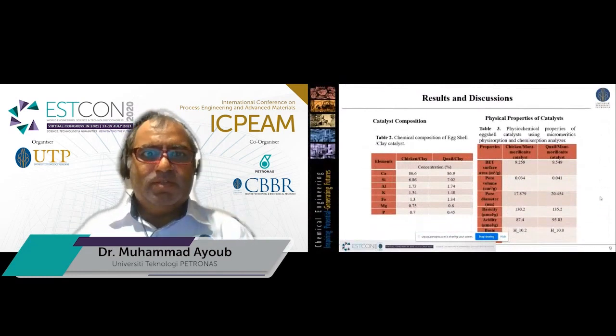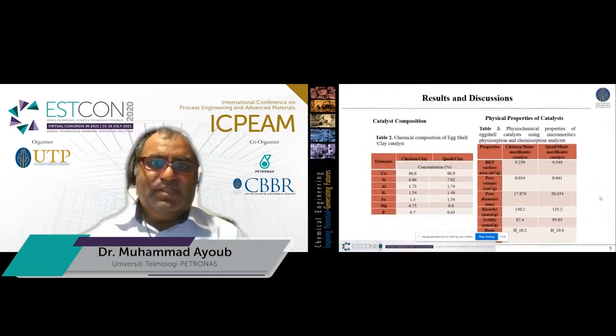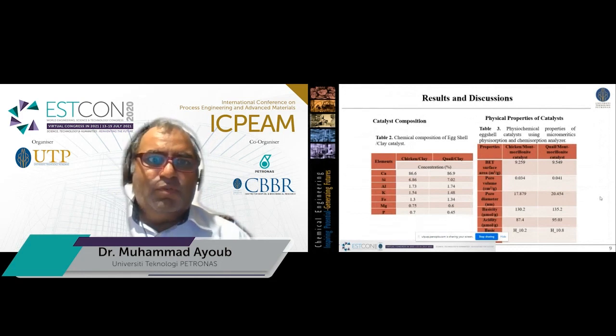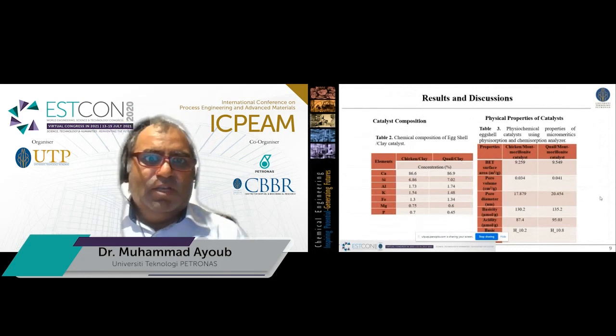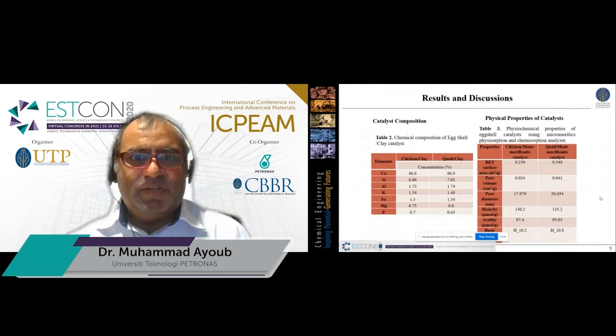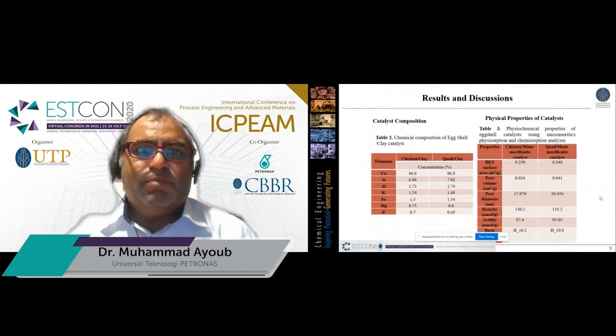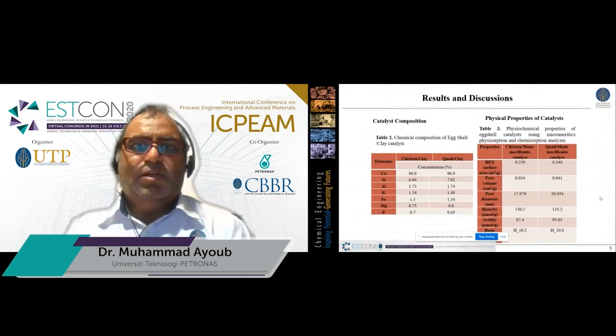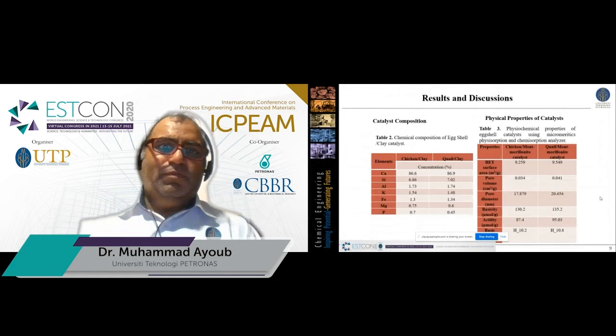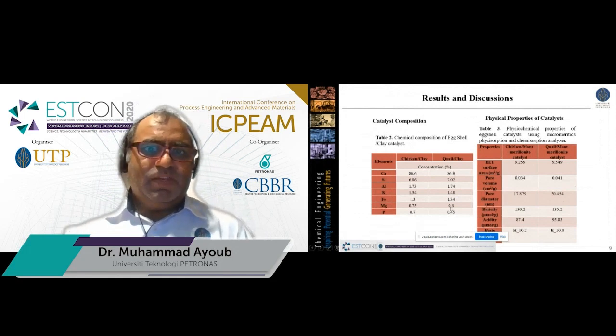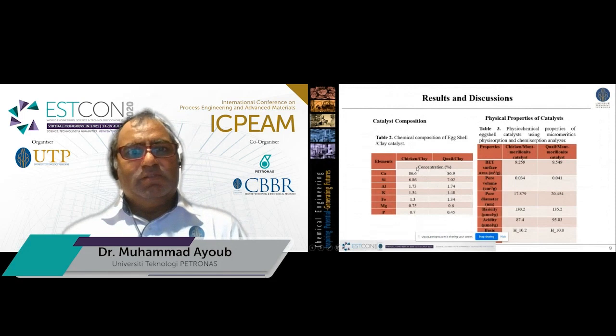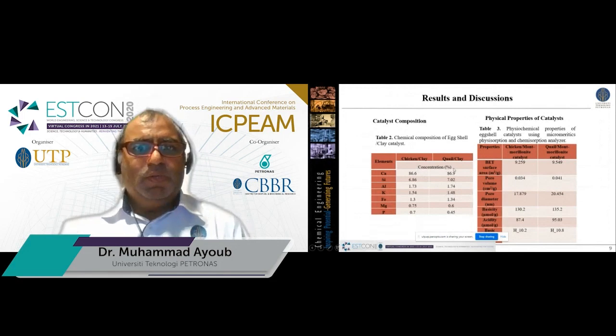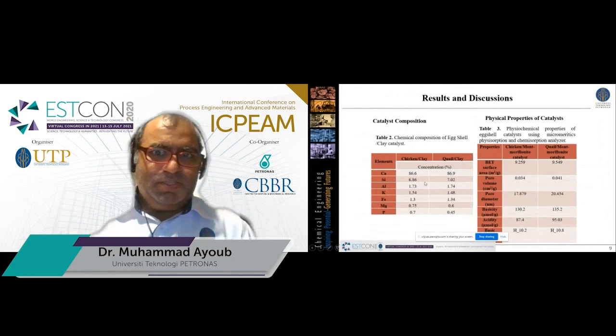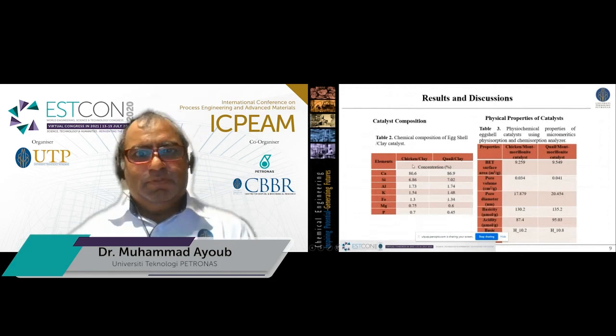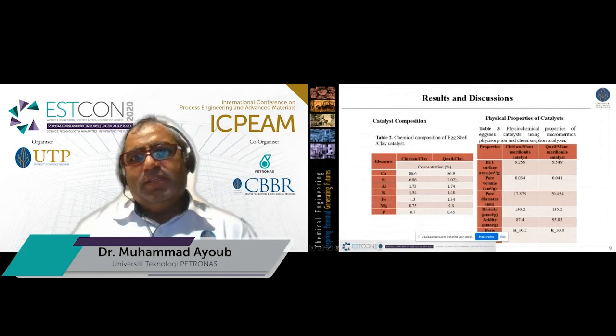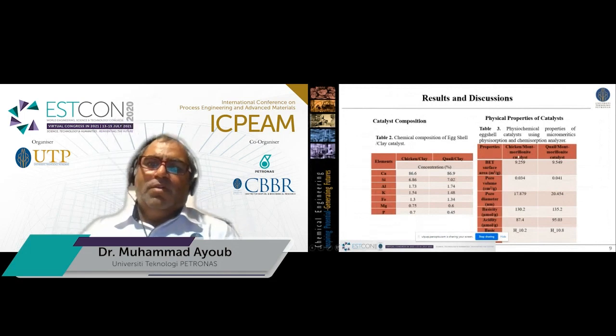We found some results we can share here. When we mix chicken eggshell with clay, we have elemental analysis, and we check that mostly calcium is utilized. We also checked another type of eggshell, quail eggshell with clay. We can see that the properties are very close, not too much difference between chicken and quail, just a slight difference. So we can say that we can take any type of eggshell combined with clay to get our final product in the form of catalyst.